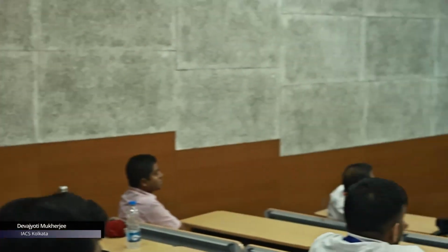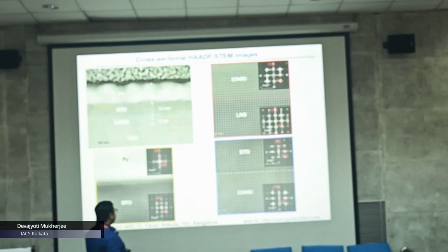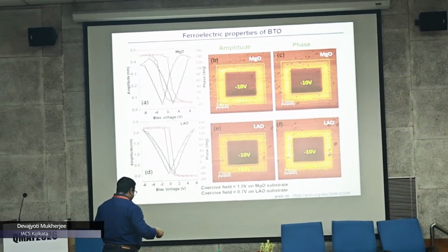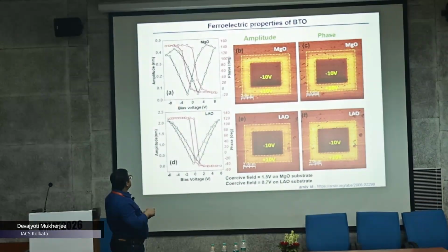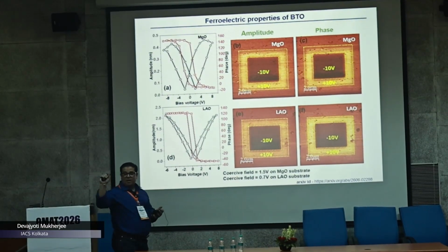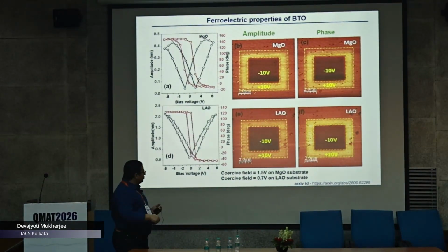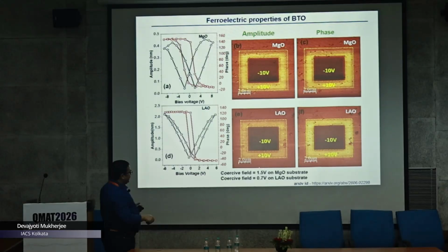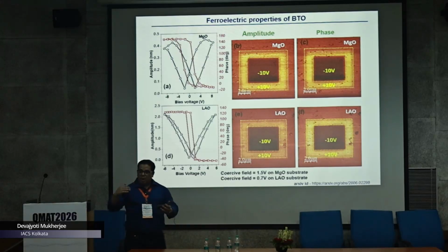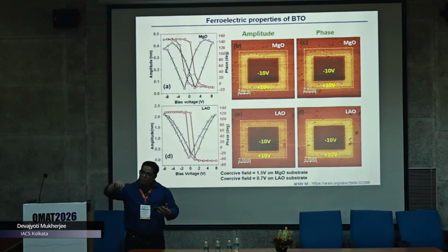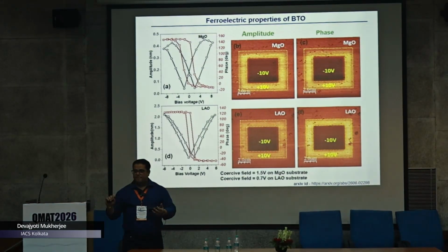Actually, that's a fantastic observation. You caught a very good point. So here I didn't mention, but when we did this coercive field of barium titanate, you see the coercive field in one case is very large, and in one case the coercive field is very small. And what we are saying is that the Rashba spin orbit coupling is related to the polarization of BTO, right?